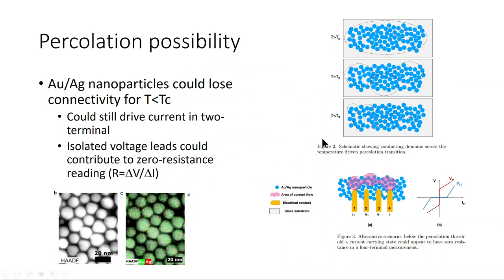So basically what we surmised is that because this is a network of nanoparticles that are basically touching one another, if for some reason there is a relative expansion, say, of the substrate, they could start to move apart from one another, and that could be driven by temperature. And if that happens, then there's a well-known percolation transition where the conducting islands break up, and they become smaller than the system size below, in this case, some critical temperature. So what we were thinking was that if that was indeed happening, you could still drive current through the system if you applied a large enough current, or you source enough voltage.